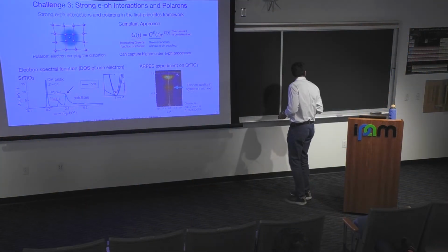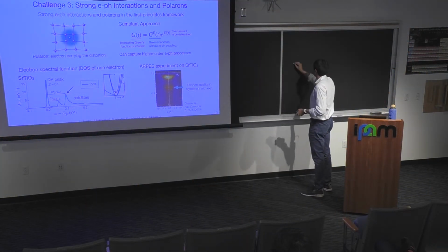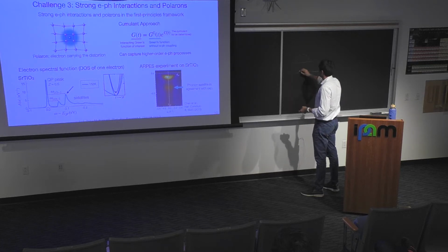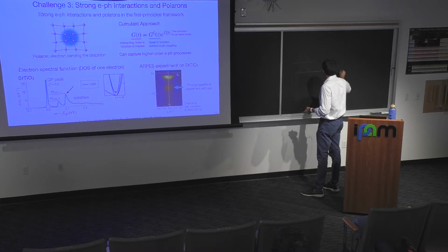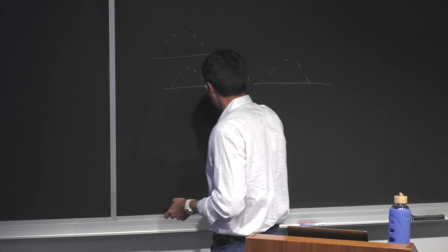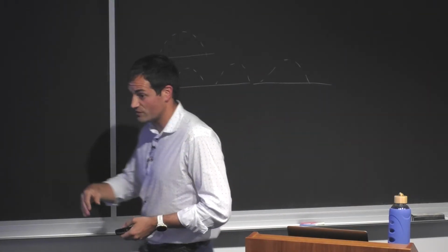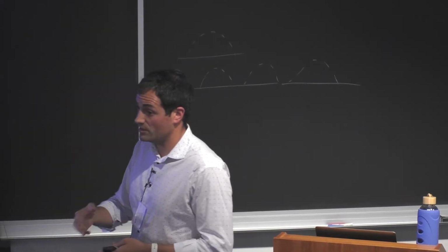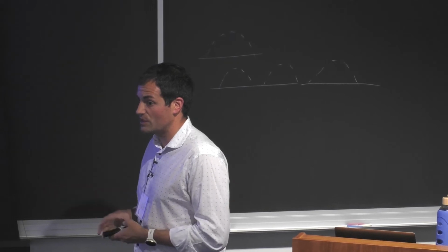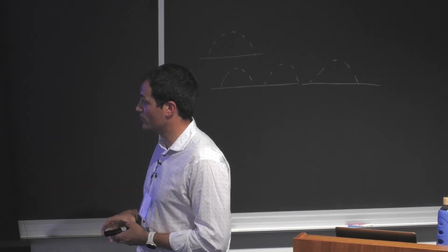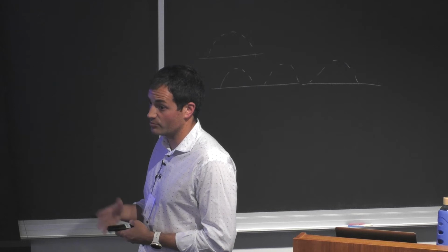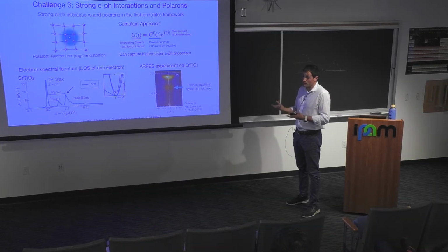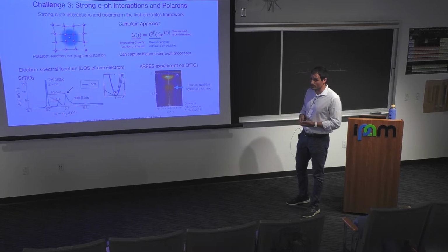So when you do it in the cumulant, it basically gives you the inclusion of all these improper diagrams where at order n, this self-energy is repeated n times. So this is one family of diagrams that are higher order. And it basically shows that these higher order effects are important. And so this is what we call polaronic effects, because they basically go beyond the lowest order theory.